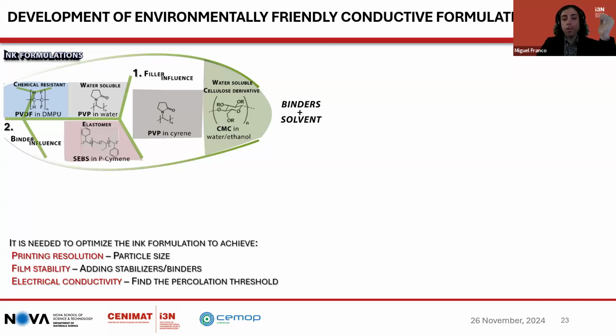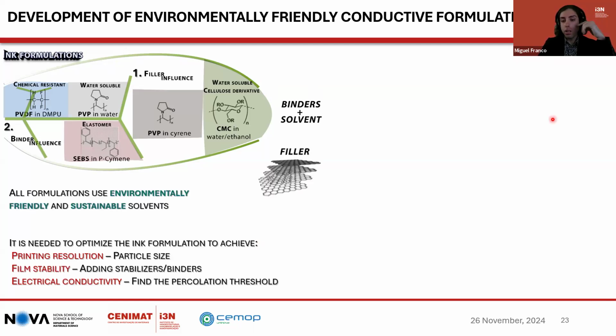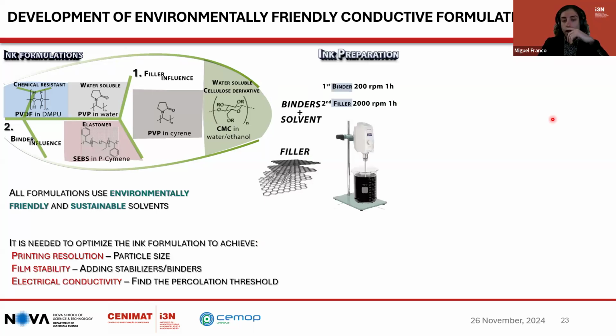In this case, our graphene formulations use the same protocol. It used mechanical mixing, which can be easily scaled into large volume. First, the binder was added at low rotation speed, and then graphene was added at maximum mixing speed. In this case, 2000 RPM, because it was limited by the equipment itself.